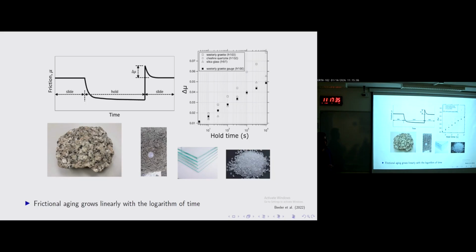What they found is that delta mu, remember, the frictional aging, increases linearly with the logarithm of hold time. So for longer and longer hold times, you see an increase. That means you're seeing a healing, or an increased frictional resistance, dependent on time. And it's linear. This is true for a whole range of materials, whether we're talking about granites, carbonate rocks, crushed rock, glass, polymers. This works well with many different types of materials. So it looks like we're capturing some general physics here that control this process. So remember, frictional aging grows linearly with the logarithm of time.